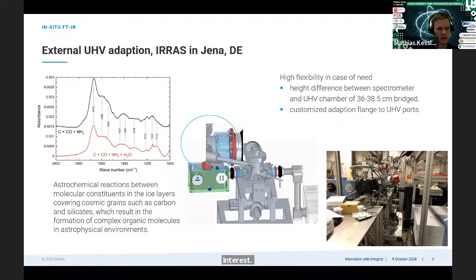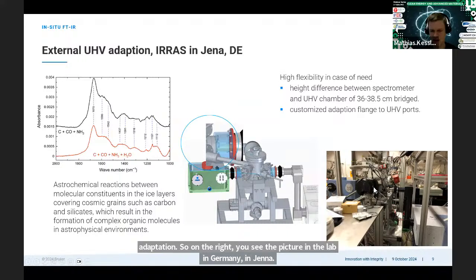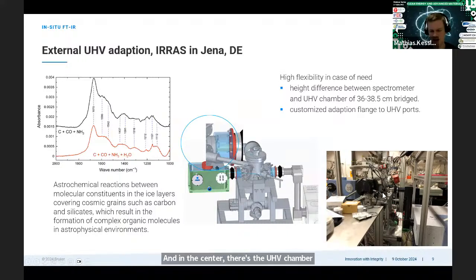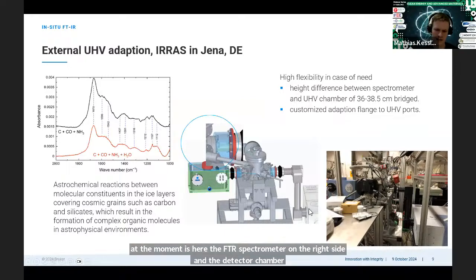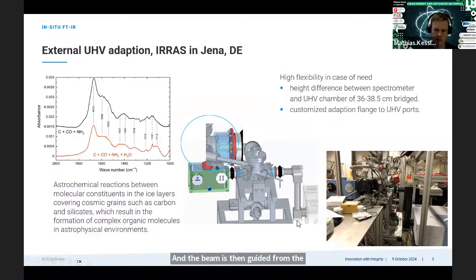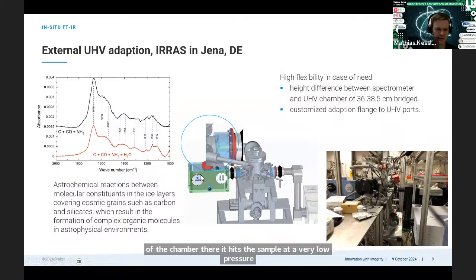I want to show you two examples for such a UHV adaptation. So on the right, you see the picture from the lab in Germany, in Jena. And in the center, there's the UHV chamber. We have different systems attached to it. And for us, the interesting part at the moment is the FTIR spectrometer on the right side and the detector chamber on the left side. And the beam is guided from the FTIR spectrometer upwards with a mirror optic, and then it's guided inside of the chamber. There it hits the sample at a very low pressure, and then the beam is reflected and goes to the detector chamber.